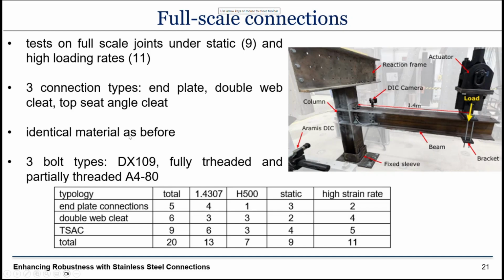So we used identical material as before, and we used 3 different bolts. We used a DX109 bolt, the high strength stainless steel bolt, and we used A4-80 bolts under 2 conditions, both fully threaded and partially threaded. The reason for that is that the thread forming process causes an increase in ultimate strength in stainless steel bolts,